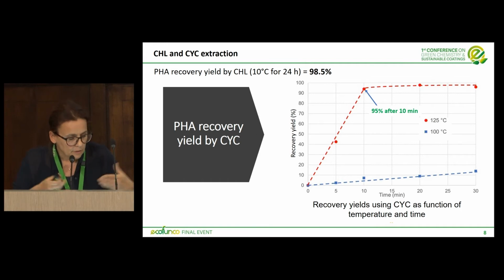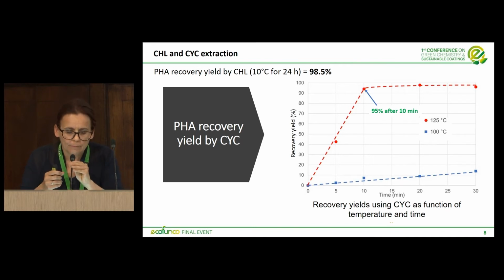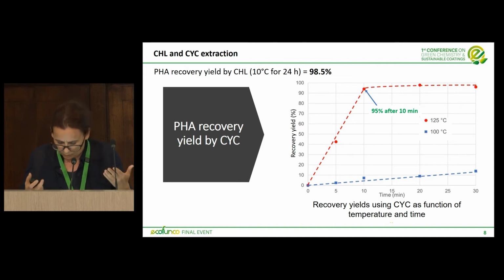As expected, in the case of chloroform, we have obtained a very high PHA recovery yield, 98.5%. But very good results have been obtained also by using cyclohexanone at higher temperature. In fact, at 125 degrees, after just 10 minutes, we have obtained a 95% recovery yield of PHAs, very high. And just after 20 minutes, we obtained the same PHA recovery yield obtained by using chloroform. And of course, as shown here, the recovery yields using cyclohexanone as a function of temperature and time as well.